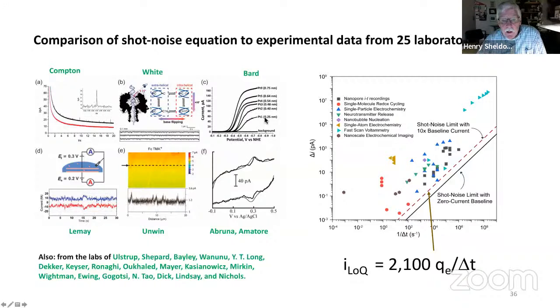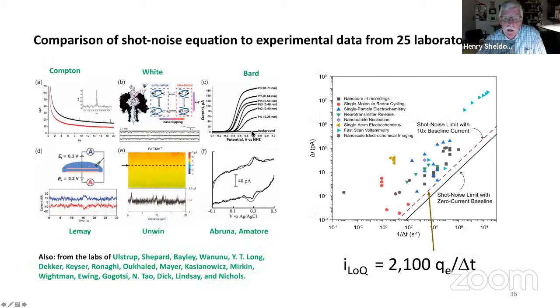The Bard experiment over here, these are voltammograms recorded at either a single platinum atom sitting on a bismuth surface, and you're looking at hydrogen evolution. This is platinum 1, platinum 2, up to platinum 9. And you can see these waves are shifting. The larger the cluster of the particle, the less overpotential you need to reduce protons. What was learned in that experiment is that there is a dramatic increase in the rate constant for hydrogen evolution as you go from platinum 1 up to platinum 9. There's a 1,000-fold increase in the heterogeneous rate constant going from 1 atom up to 9 or 20.